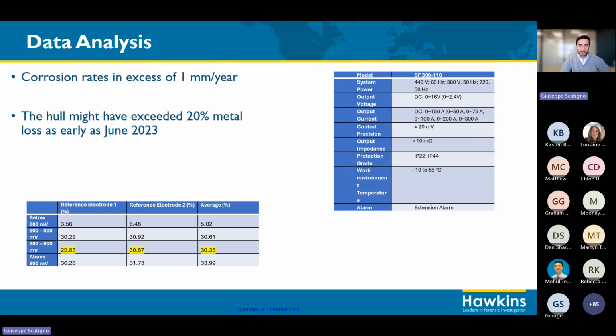I calculated that since the previous survey, we had exceeded 1 millimeter loss of metal per year, which is effectively equivalent to bare metal being exposed in seawater. So effectively, as if we didn't even have painting, a coating, which is on all hulls. And this might have already been significant in June 2023.